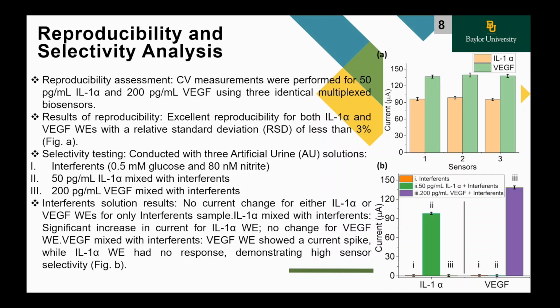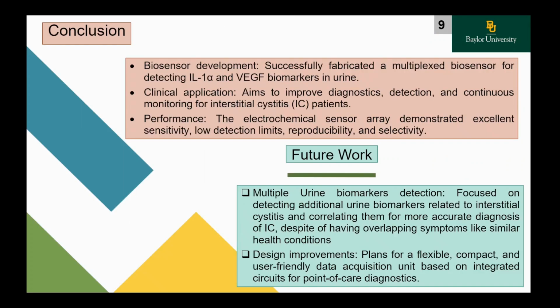Interferent solution results show no current change for either interleukin-1 alpha or VEGF working electrode for only interferent sample. Interleukin-1 alpha mixed with interferent sample introduced significant increase in current for interleukin-1 alpha working electrode, but no change for VEGF working electrode. For testing using VEGF mixed with interferent sample, VEGF working electrode show a current spike, while interleukin-1 alpha working electrode had no response, demonstrating high sensor selectivity for both sensing electrodes.